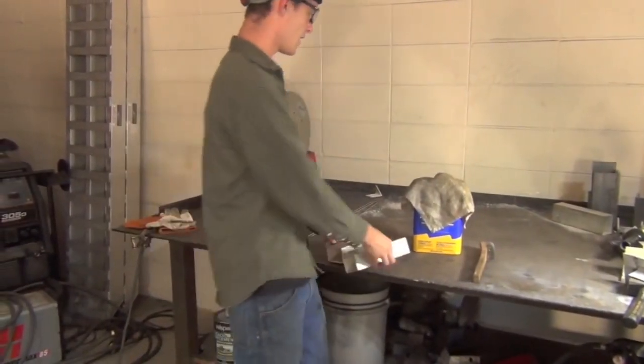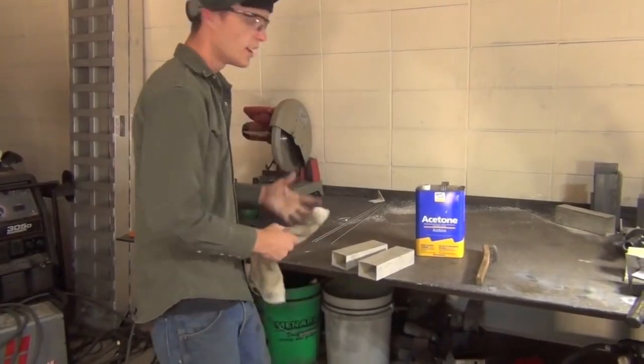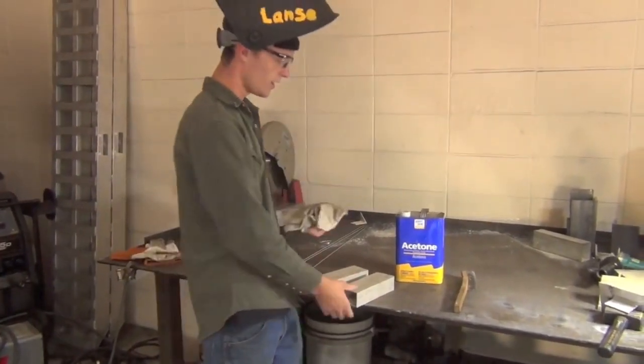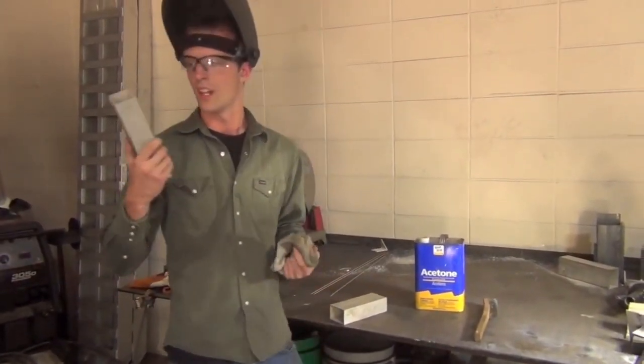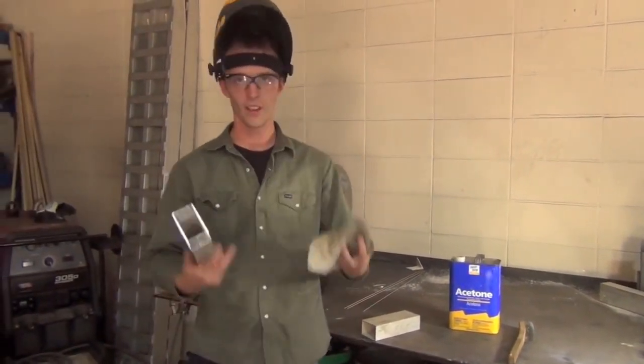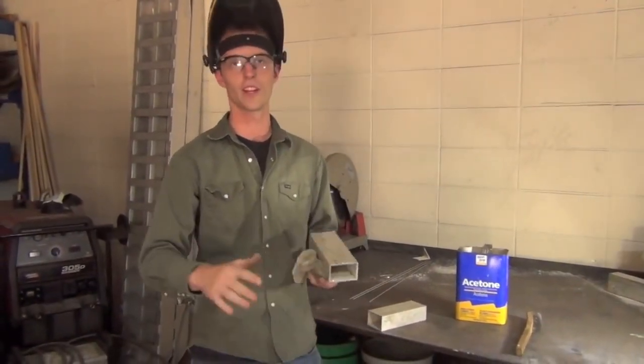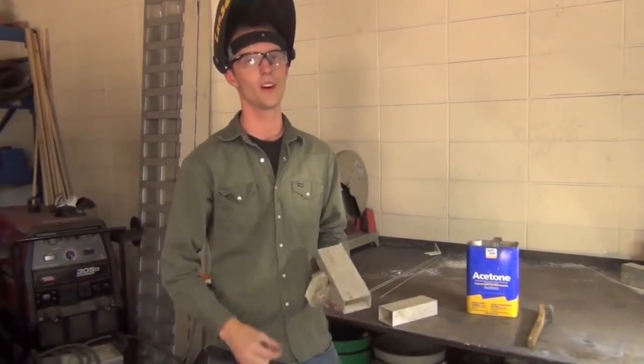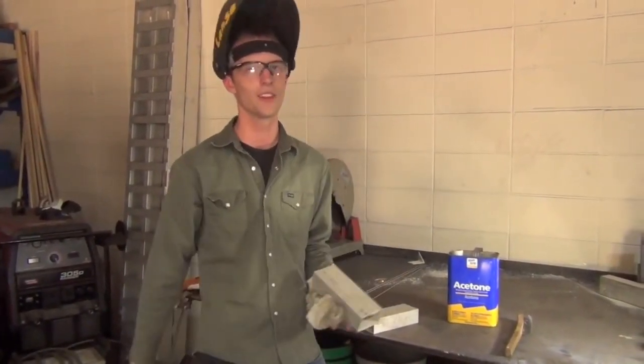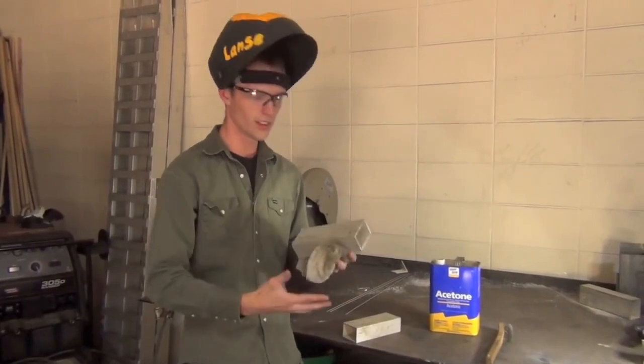And basically, you're going to want to do something to deal with the oxide layer. The aluminum oxide layer is a very hard to go through layer of material that's on top of the regular aluminum metal. It's very, very small, like several thousandths of an inch. I can look up the exact number. And it's a little bit hard to weld through.